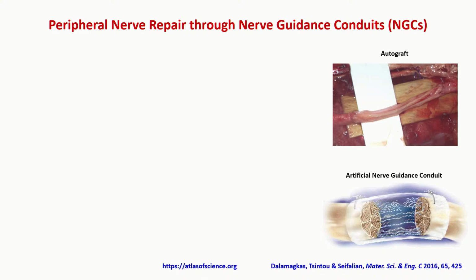In that case, try to impose a nerve guidance conduit through this gap, and then somehow promote extension of nerves and cover the gap, and eventually recover the functions. So this concept of nerve guidance conduit has been around for several decades. There are some commercial products in the market already, but most of them don't have a good outcome, okay? Because right now, this kind of conduit is just like a piece of polymer tube, actually. In many cases, they don't really support the growth or extension of axon nerves, actually. So that has been problematic. In particular, when this gap is large, typically like 40 millimeters, this kind of tube definitely will fail.